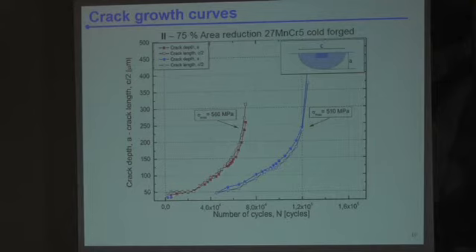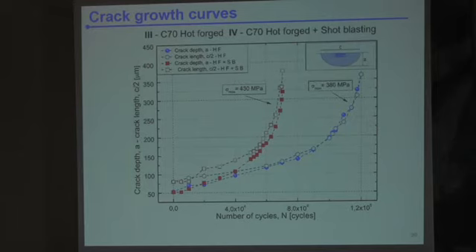Maybe one difference is that you get cracks a little bit later depending on your strain level in the material. Again, this is exactly what we saw when we looked at the pictures. The cracks are very regular, and you could predict the depth looking just at the surface. This is what it tells you. For material number 3 and 4, there is, however, a slight difference.